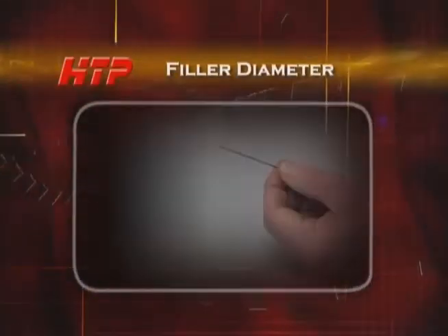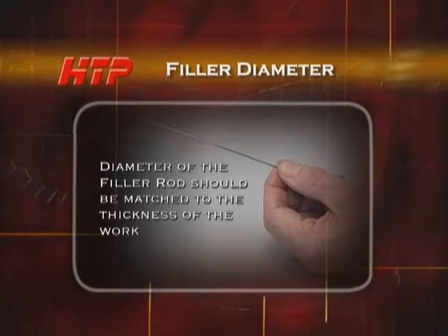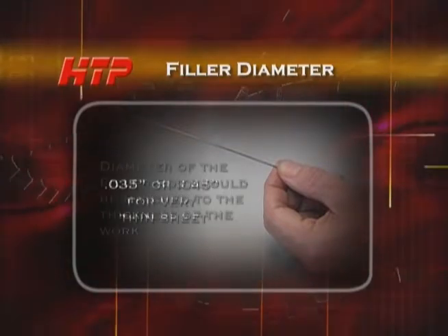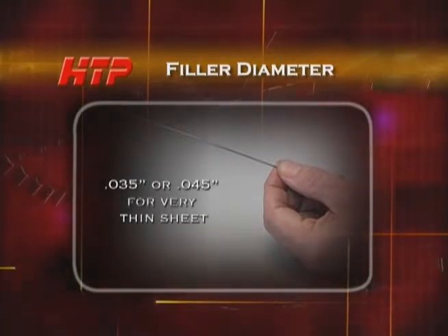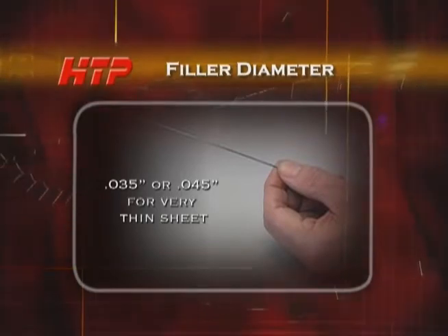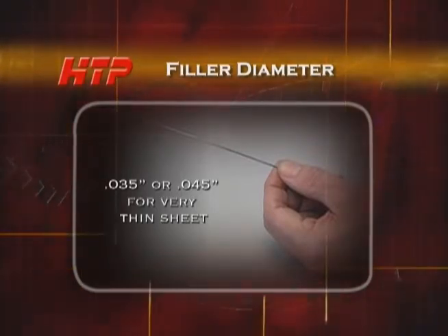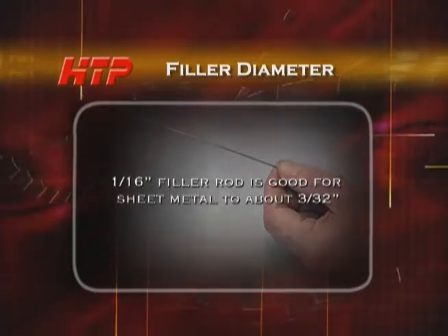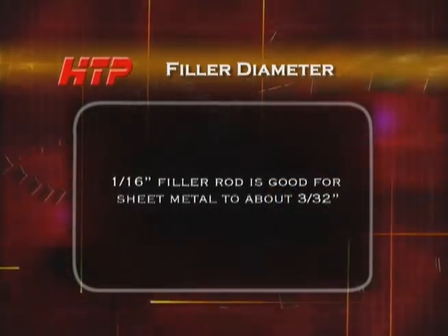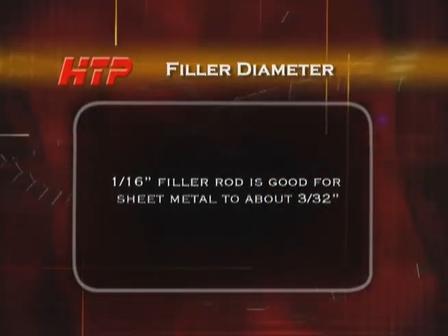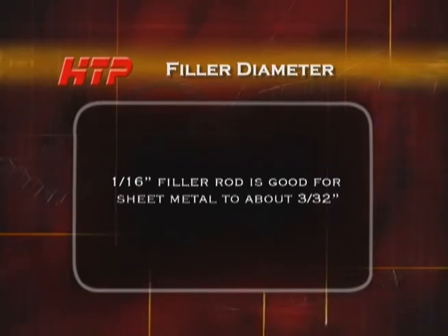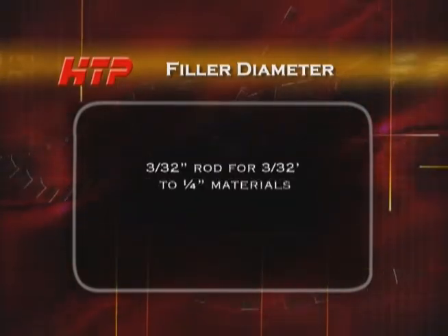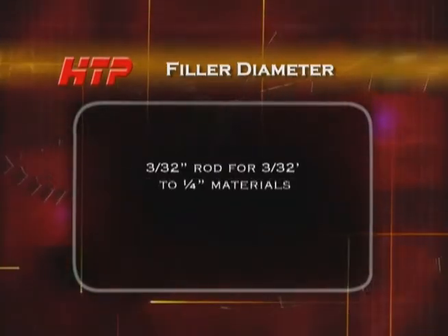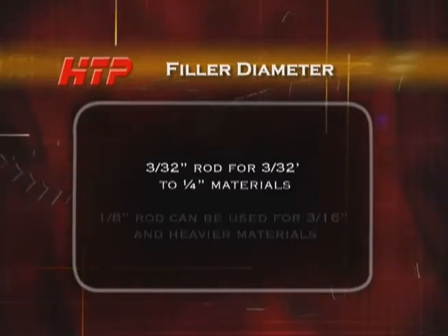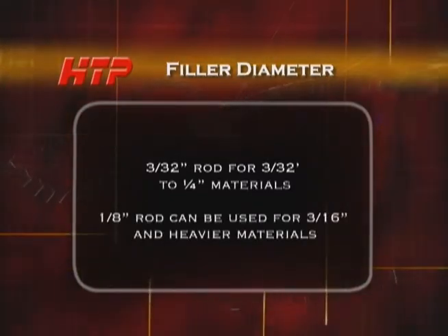Like tungsten, the diameter of the filler rod should be matched to the thickness of the work. Use a thin 035 or 045 for very thin sheet. MIG wire can even be used. 1/16-inch filler rod is a very common diameter and is good for sheet metal to about 3/32. Use a 3/32 rod for 3/32 to 1/4-inch material, and an 1/8-inch rod can be used for 3/16 and heavier materials.